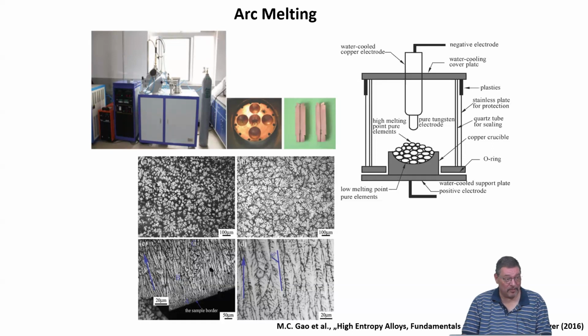This is a very common problem, yes, that the copper diffuses into the material because the copper is water cooled. But if you go to very high temperatures of your ingot, if you maybe are melting high melting point materials, you will not prevent copper going into the material because the heat cannot be taken out so quickly. Then arc melting is really a difficult problem. If you don't want to have copper in your material, it's very difficult to prevent. So for me, that method is good for something up to the melting temperature of iron maybe, but if you go higher, it is very difficult.